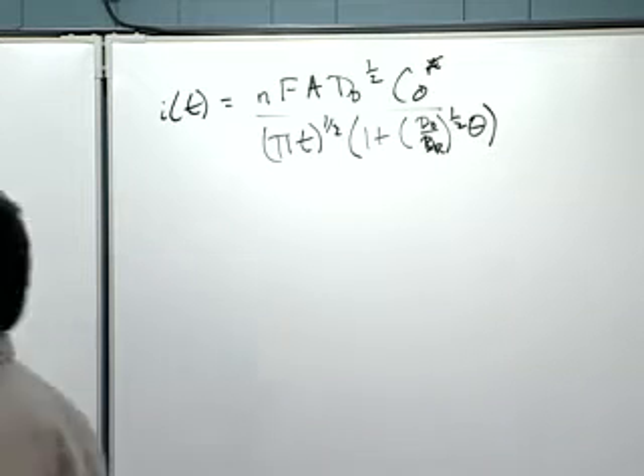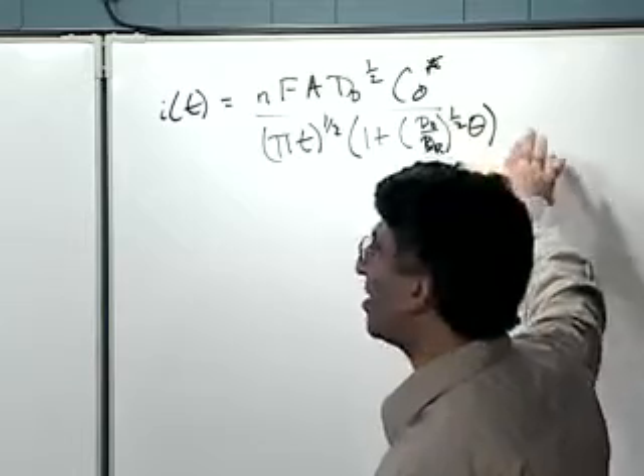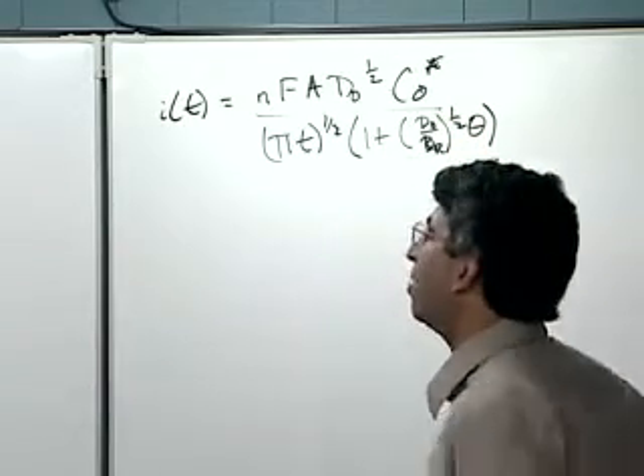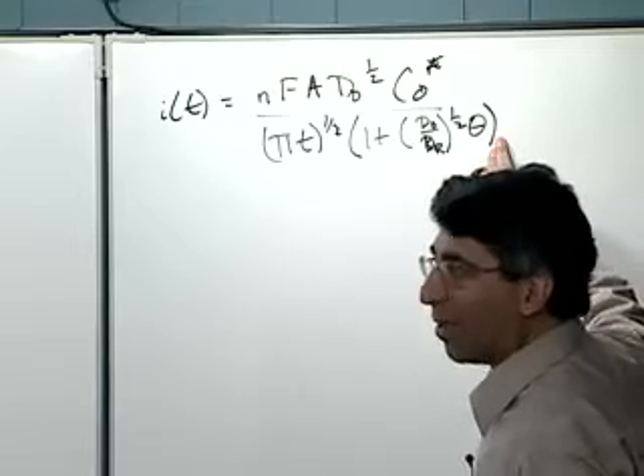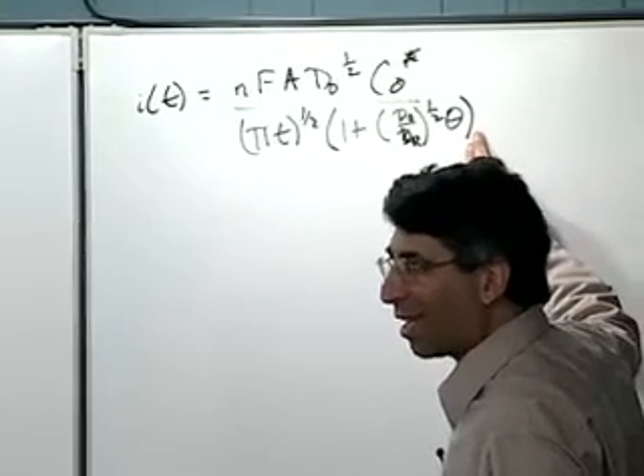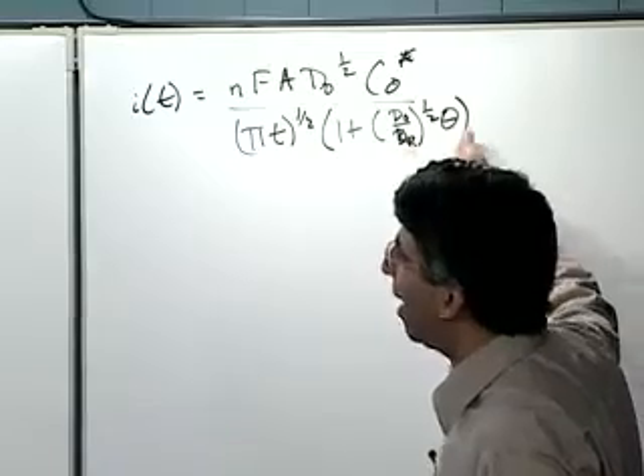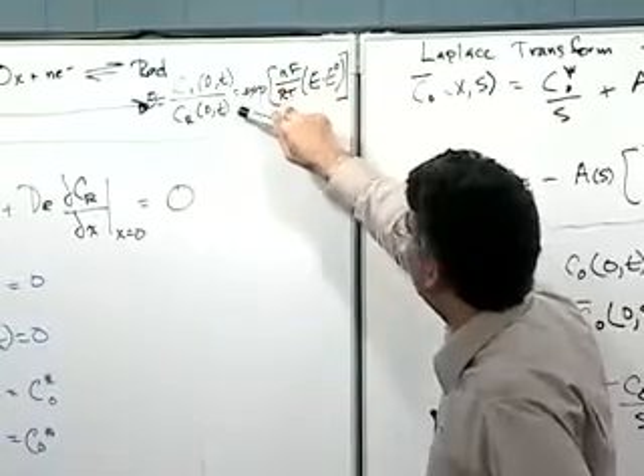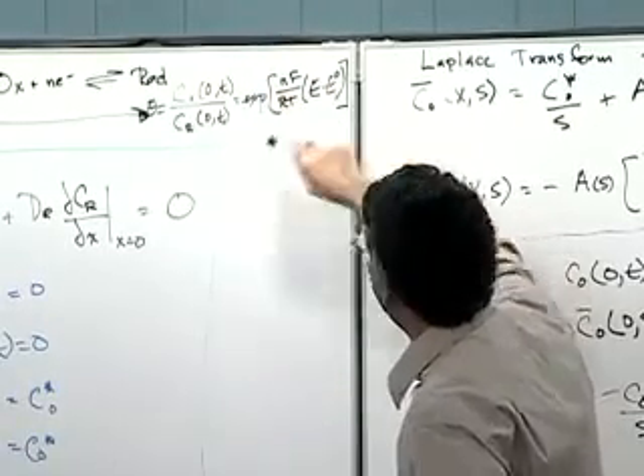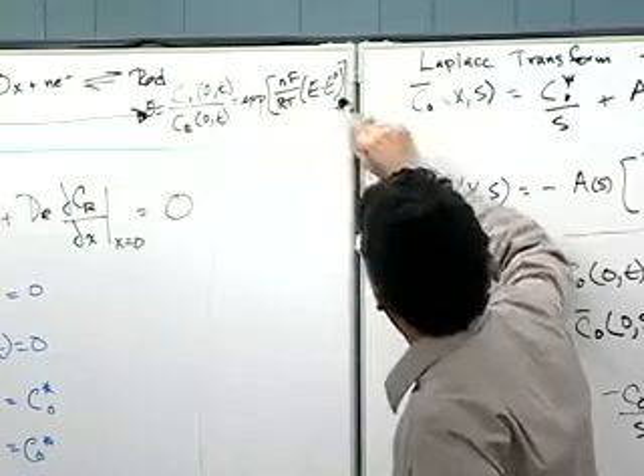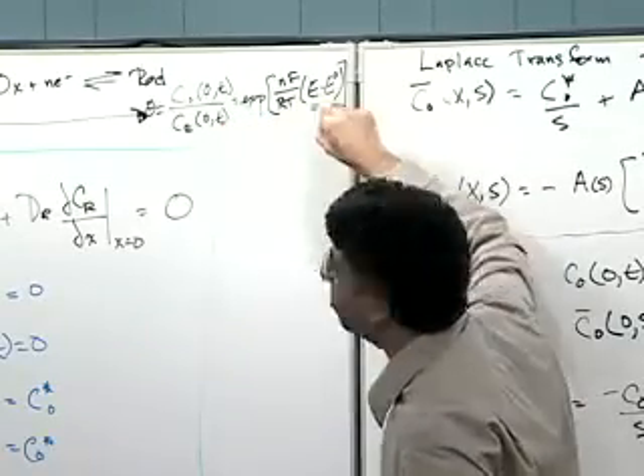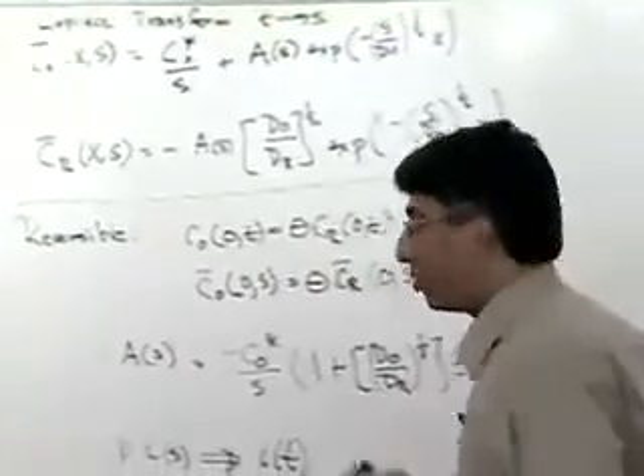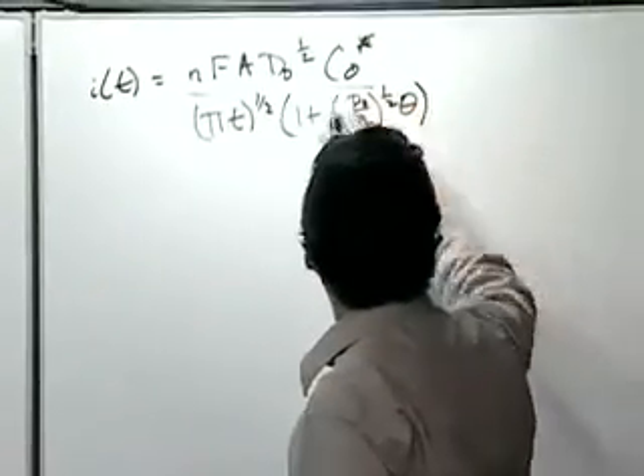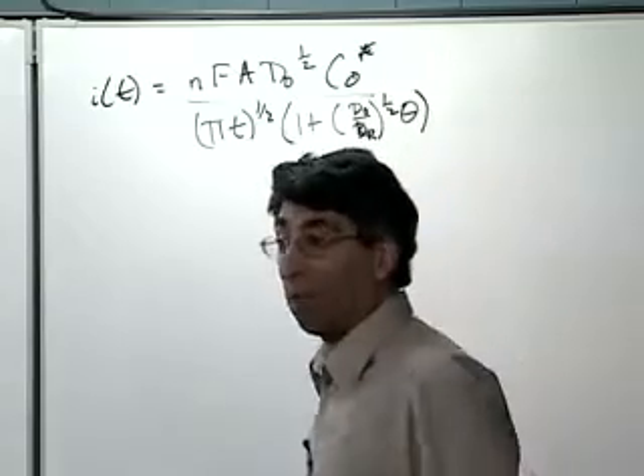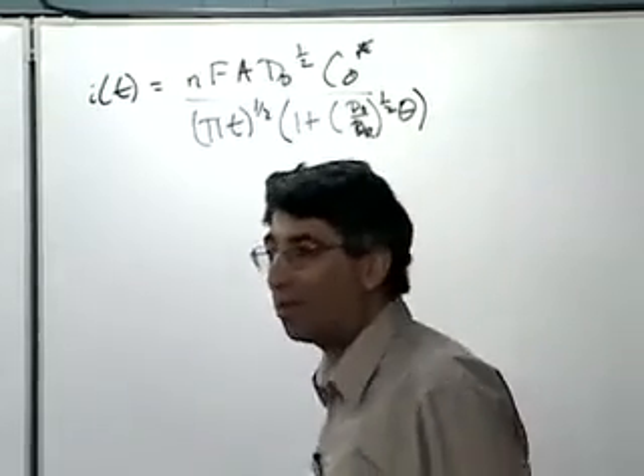Okay, and you will notice that theta, given by the Nernst equation over there, travels between essentially 0 and 1. That is, I can get other ratios. But at some point, if these two concentrations become too different, even though this equation would say I can get any ratio of concentrations I want here, I, in fact, don't have enough of one species around to maintain this potential. So theta is always going to be a positive number, and it's going to be a number somewhere around 1, let's say. By that, I mean with an order of magnitude of 1.